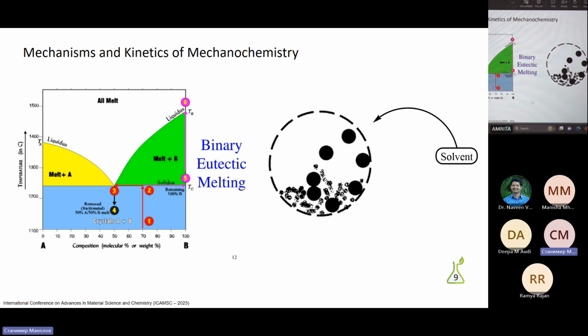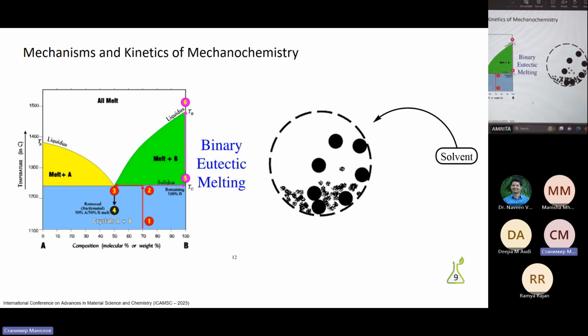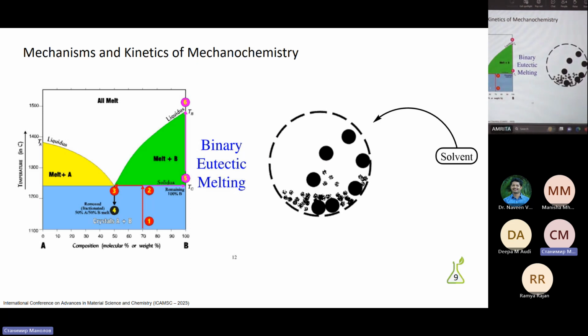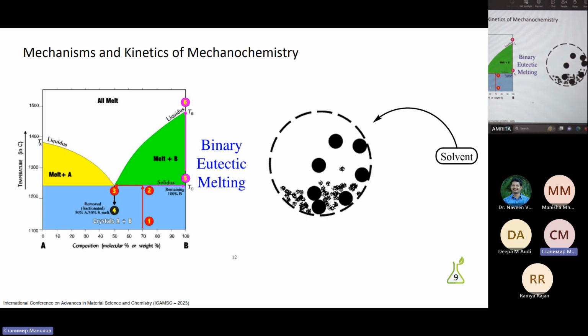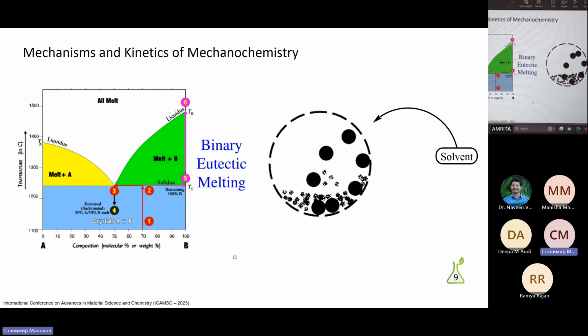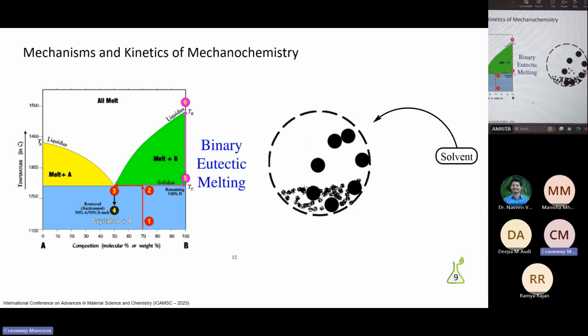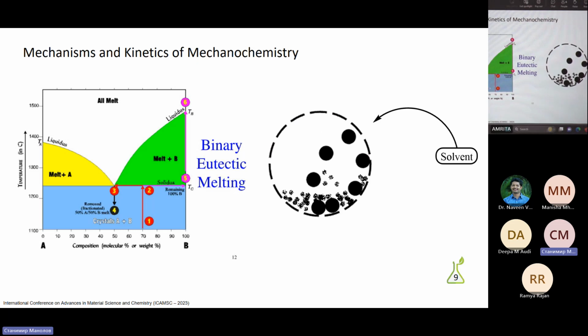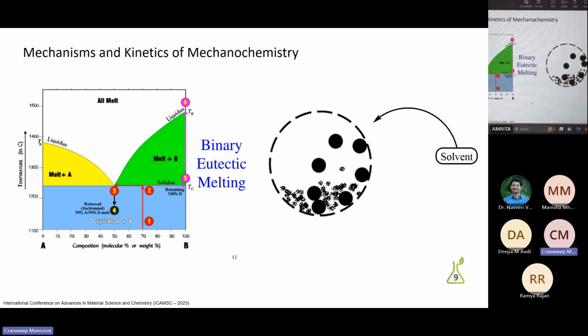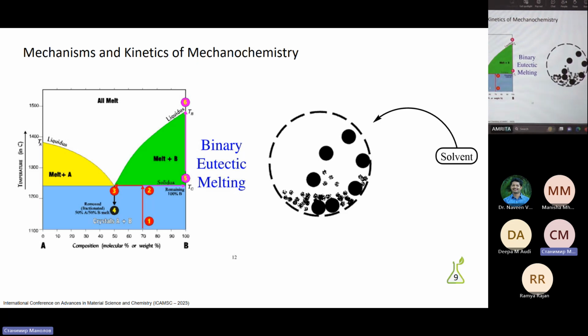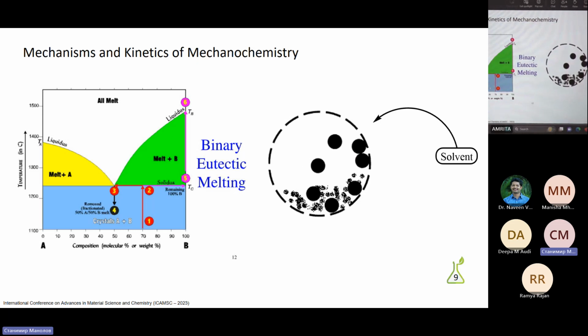Following this development, a variety of approaches and models were employed to elucidate the mechanisms and kinetics of mechanochemistry. Among these, one notable method involves eutectic melting, and the occurrence of submerged eutectic temperatures below room temperature facilitates the formation of co-crystals. Additionally, dissolution in a small quantity of liquid introduced during co-grinding, gas-solid reactions resulting from sublimation, and direct solid-state interdiffusion of components are among the other techniques utilized in mechanochemistry. However, a common challenge with these methods lies in the use of intermittent mechanical pulses, resulting in disparities between the total time and the actual time of mechanical treatment.